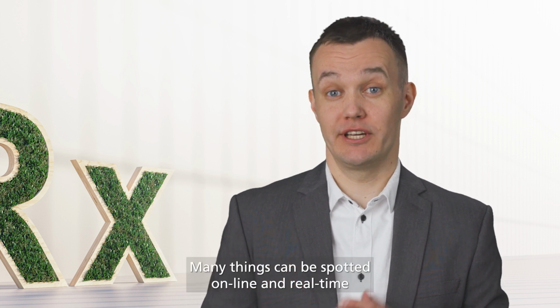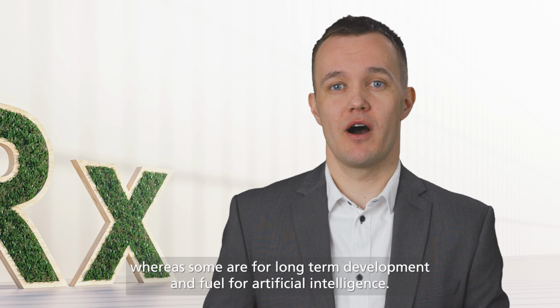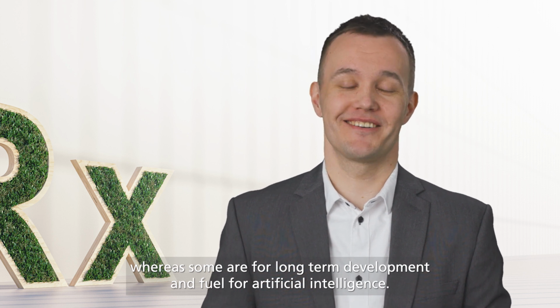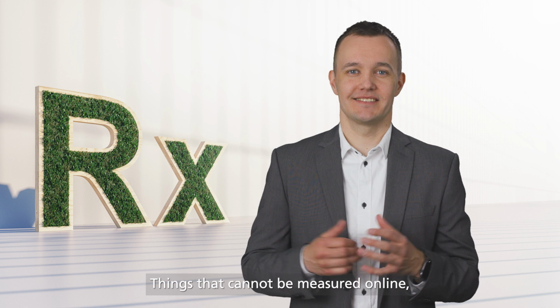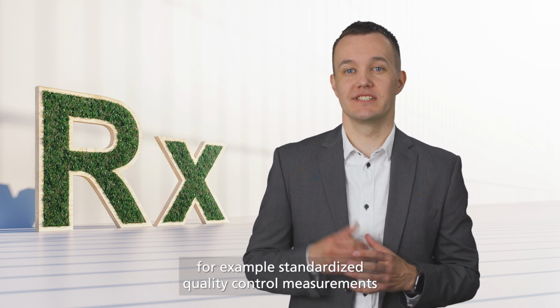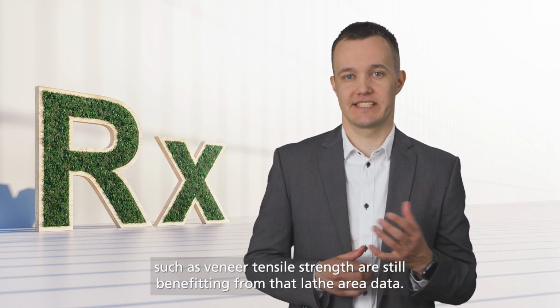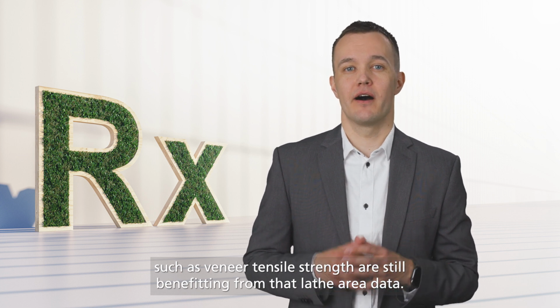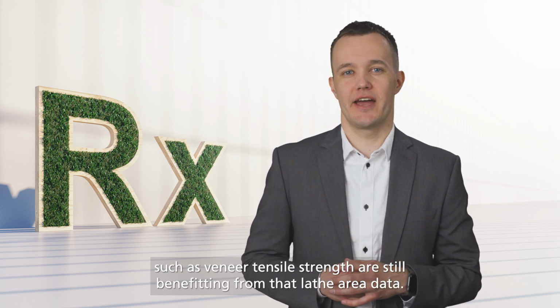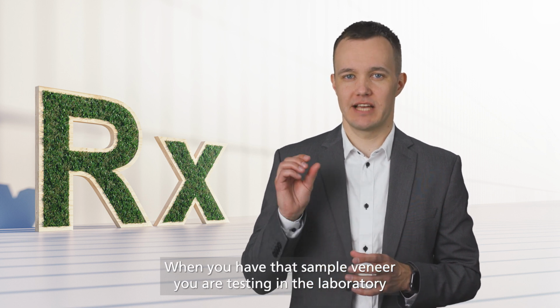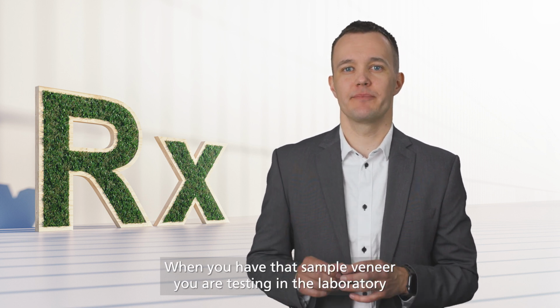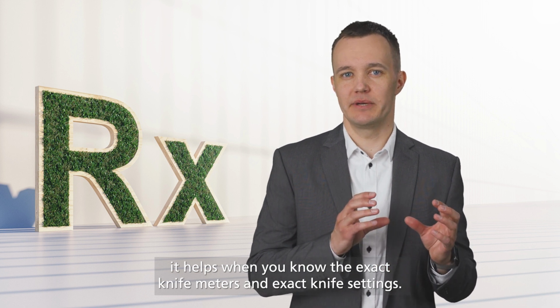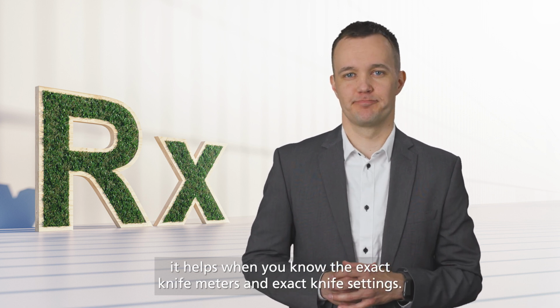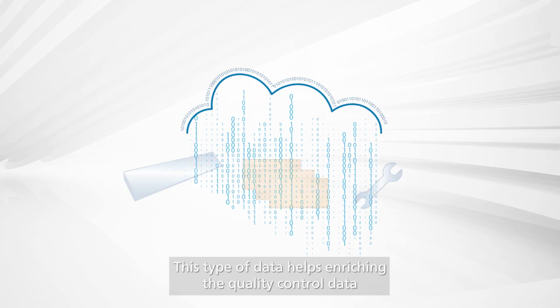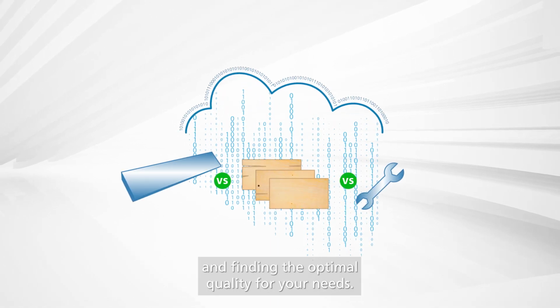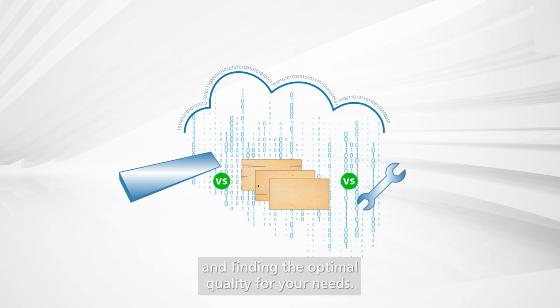Many things can be spotted online and real time, whereas some are for long-term development and fuel for artificial intelligence. Things that cannot be measured online, for example, standardized quality control measurements such as veneer tensile strength, are still benefiting from that lathe area data. When you have that sample veneer you are testing in the laboratory, it helps when you know the exact knife meters and the exact knife settings. This type of data helps enriching the quality control data and finding the optimal quality for your needs.